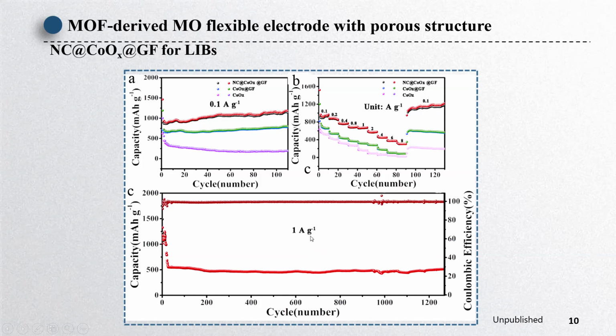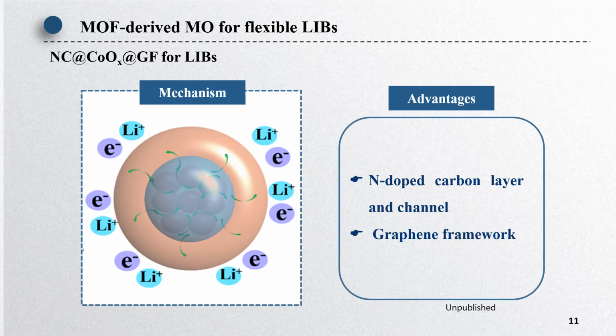The composite also showed promising super-long cycling performance. The capacity can deliver nearly 400 mAh per gram after 1,200 cycles at a current density of 1 amp per gram. The mechanism is that the nitrogen-doped carbon layers and the channels can promote ion diffusion and electron transport, and also these carbon layers can protect the metal oxide and help release the volume expansion effect of the metal oxide during the charge and discharge process. And the 3D graphene frameworks can shorten the diffusion of the ions.